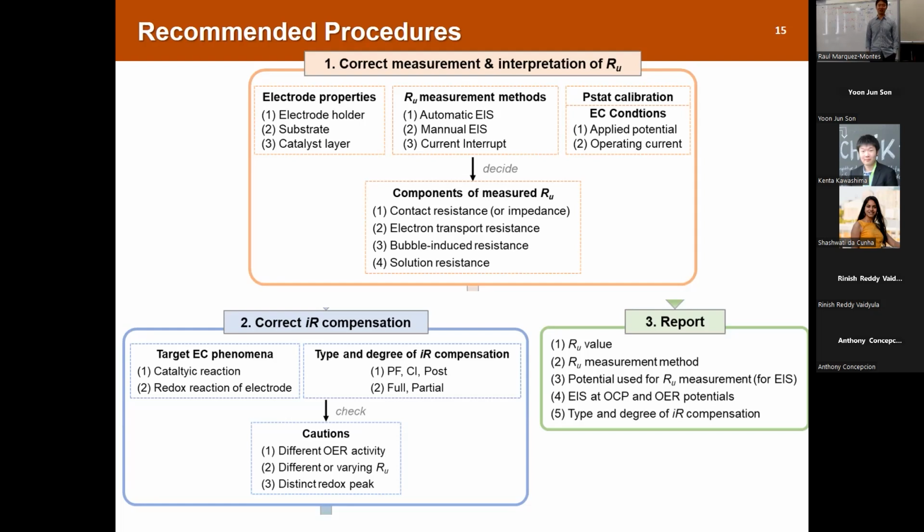There is a capillary effect. The electrolyte can go up to the current collector, and you get a different RU value. That's why I found that issue and I was like, what's going on? Why do I see an extra semicircle? So IR compensation is a super straightforward principle, but we should take care of lots of experimental factors that can mess up our analysis.